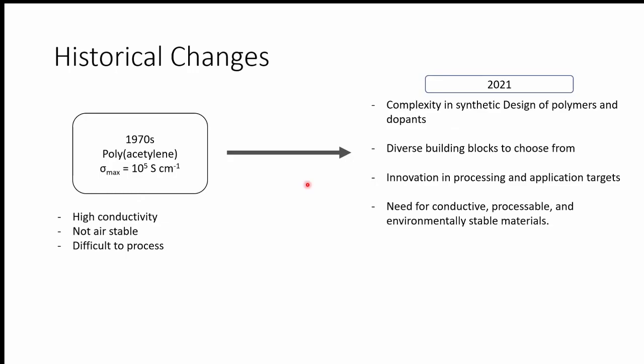Now, how has that benefited the scientific community working on conjugated polymers within the last 40 to 50 years? So in the 1970s, 3 scientists discovered polyacetylene, and then they reported its conductivity, denoted by sigma, as something on the order of 10 to the power 5 Siemens per centimeter. Now, if you see this number and you don't know the context, you'll say, well, is it good or bad? This is kind of comparable to conductivities of copper and gold and silver, because these metals have conductivities above 10 to the power 4 Siemens per centimeter. So it's very conductive. And this is why people now write grants trying to achieve metallic type conductivity, because they want to achieve values that resemble metal by employing organic materials.